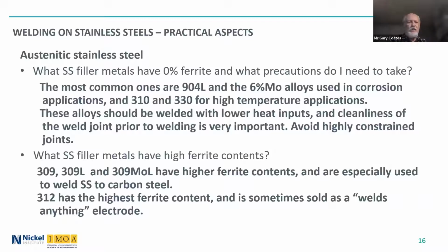312 has the highest ferrite content. It is used for more difficult to weld materials. It's sometimes sold as an electrode that welds anything, which is not true, but it is more useful and is often used as a maintenance electrode, not in chemical plants or pharmaceutical or even the food industry, but in maintenance repair shops that occasionally do a little bit of stainless steel welding. But basically 312 is a little more forgiving. It's easier to weld with. The welders like it. But because it has a very high ferrite content, you have to be very careful where you use it.